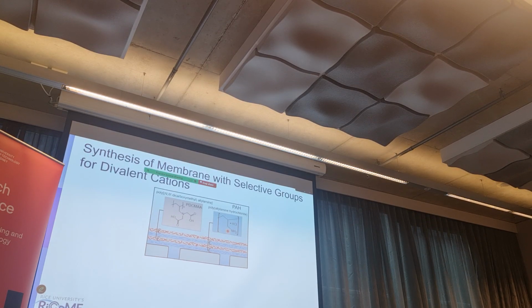And here we created a membrane for divalent cation separation. I'll show you later mostly about transition metals like copper, nickel, cobalt, and zinc. We selected and created a polymer, an anionic polymer, which has what we call iminodiacetate groups. These are two carboxyl groups and a nitrogen, which have very, very strong binding to divalent metals. I'll show you some data soon.